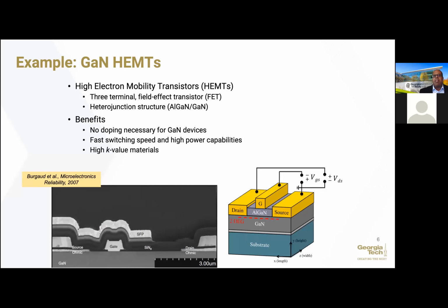So if I start out with a gallium nitride high electron mobility transistor, these are used for both RF as well as for lateral devices. You can use these for power. What's interesting here is that no doping is needed for gallium nitride devices in the form of a HEMT, because I have piezoelectric polarization from this AlGaN layer. What that does is draw electrons very close to this interface between the AlGaN and the GaN. So I get what's called a two-dimensional electron gas, and I don't have to dope this. Just based upon the structure, I can create a nice sheet charge of carriers that I can then manipulate and form my device. So we get very fast switching speeds and high power handling capabilities. This is really nice for these types of devices.